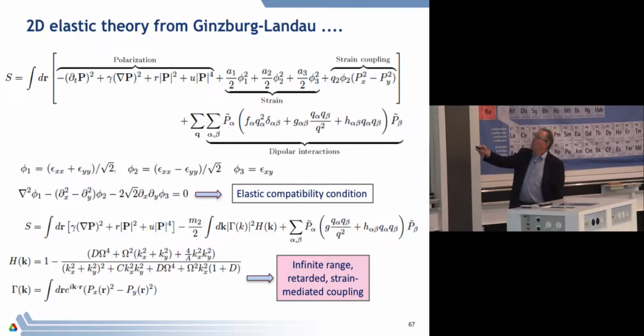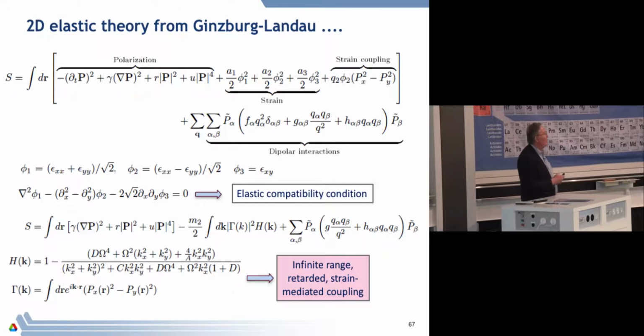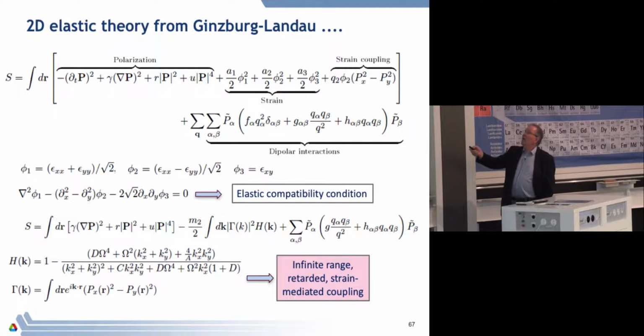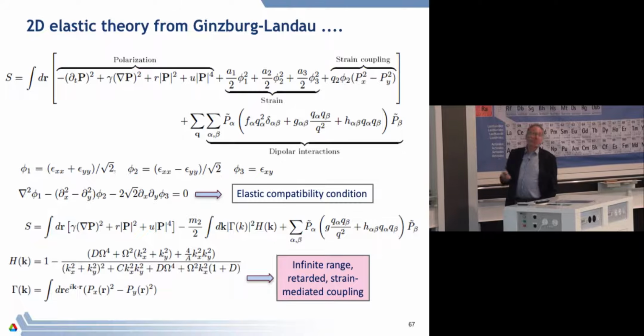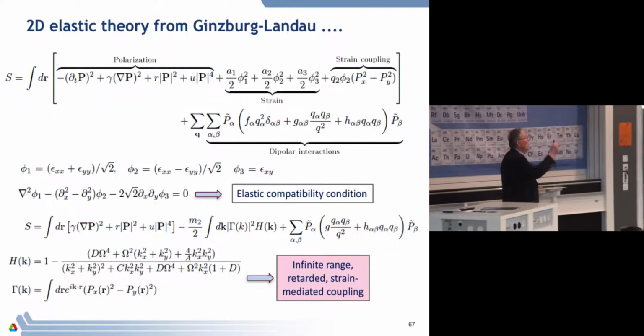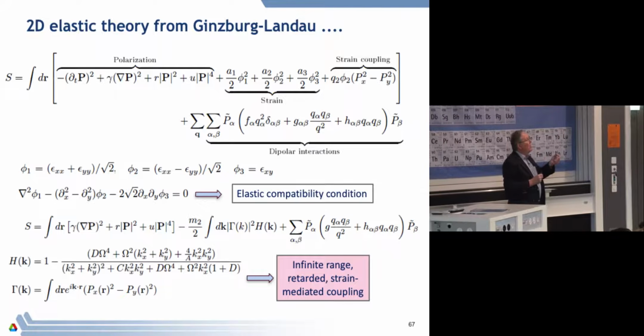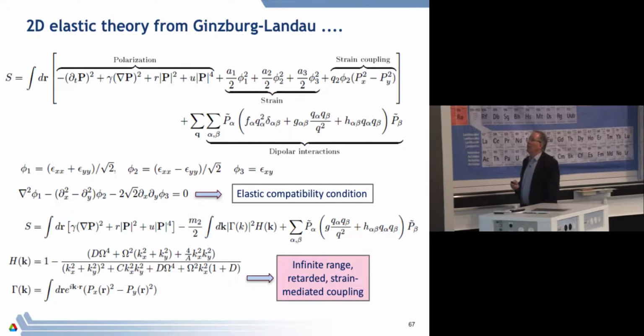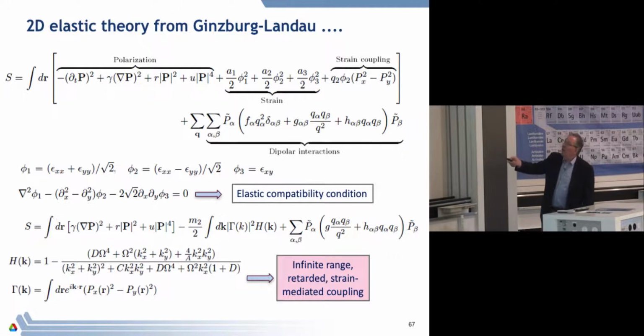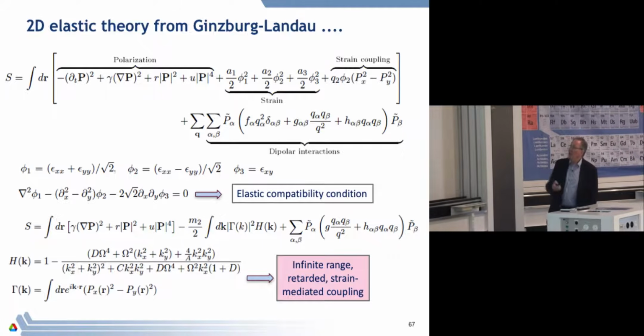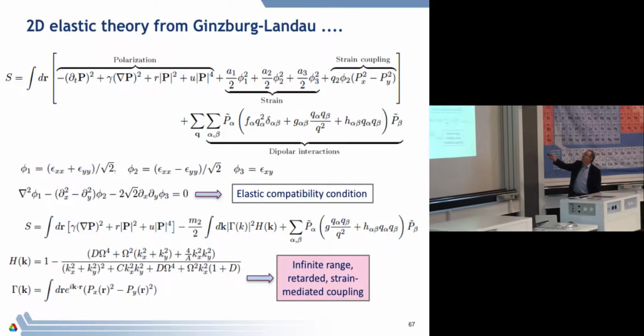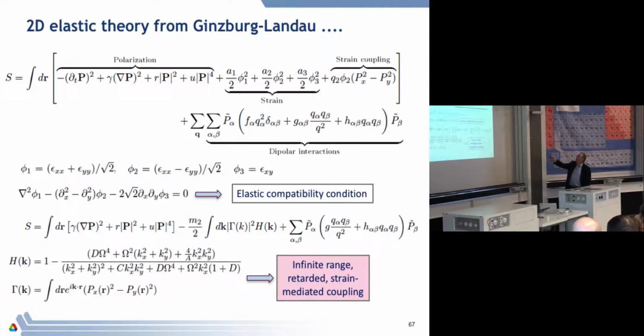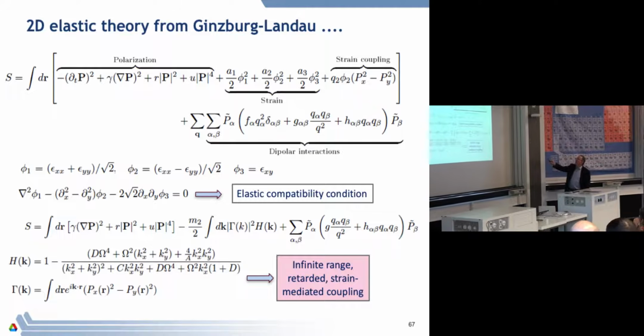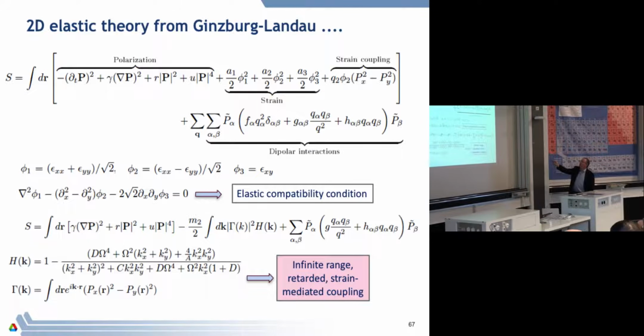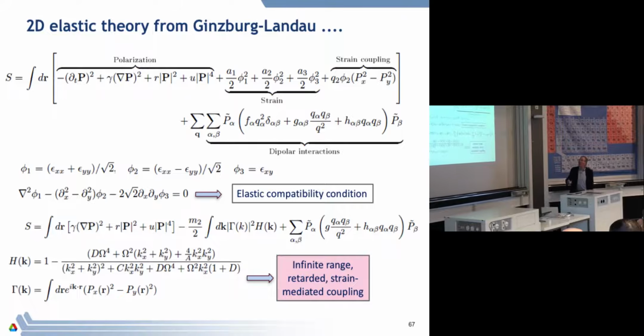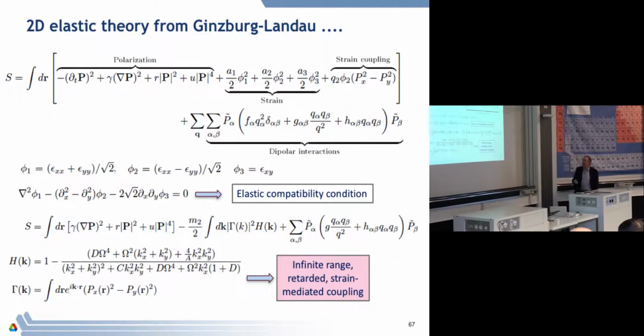So how do I solve this problem? Well, free energies are there to be minimized. So I would get rid of the strain in terms of the polarization by saying, for any given polarization, let me make sure that I know what strain is there. And so I can get rid of the strain term, and I can solve that with this condition on part of it. And of course, because this couples to a square, after I minimize, I'm going to get that phi goes like p squared, and therefore this energy term is eventually going to look like something which goes like the fourth power of the polarization, so it's like a U term over here.